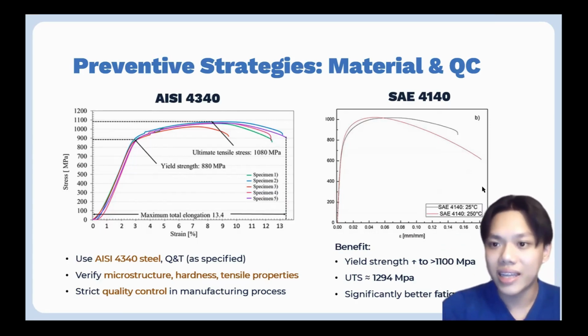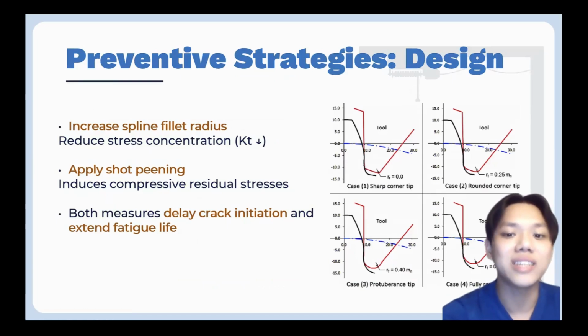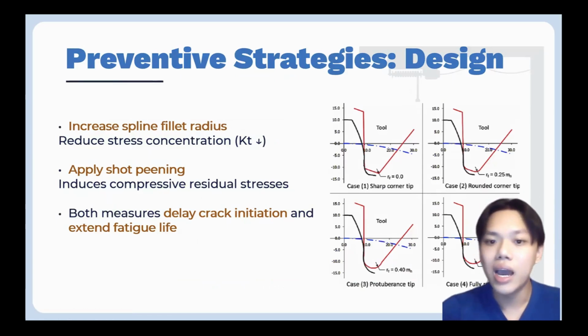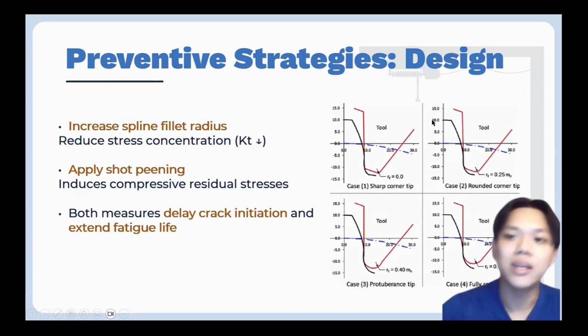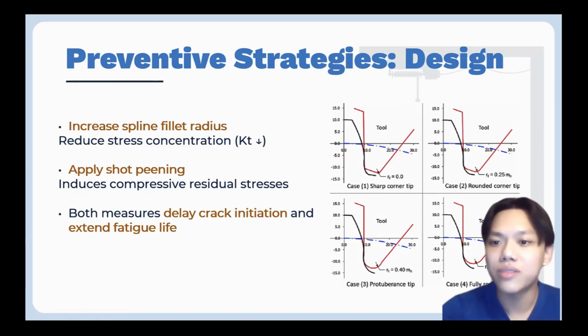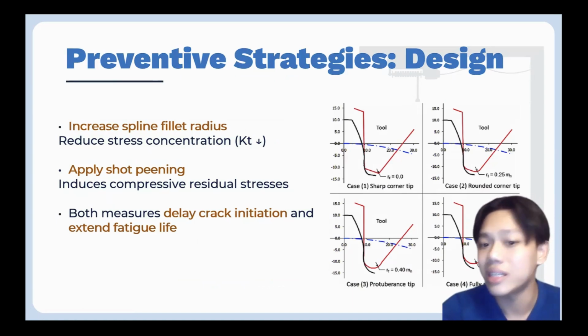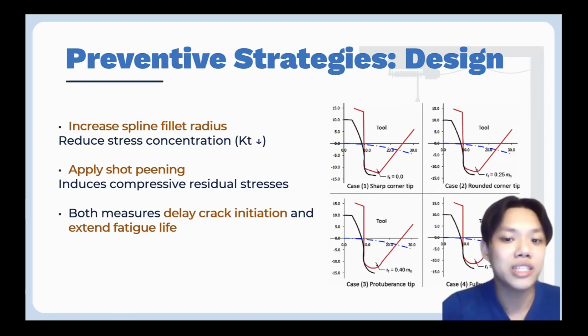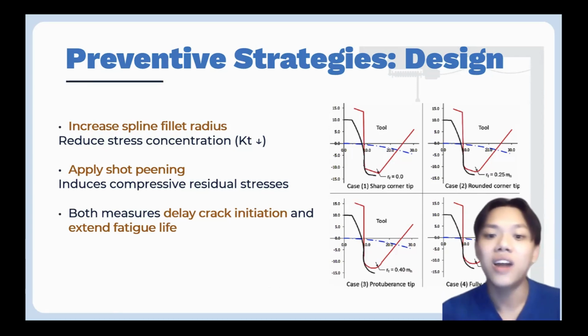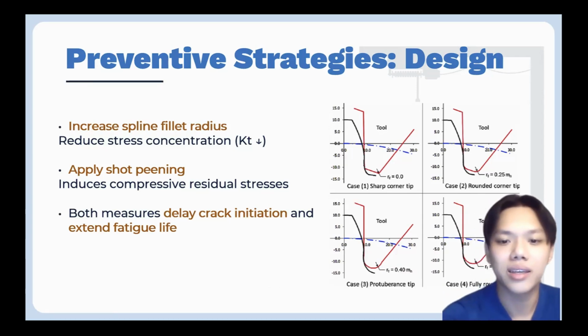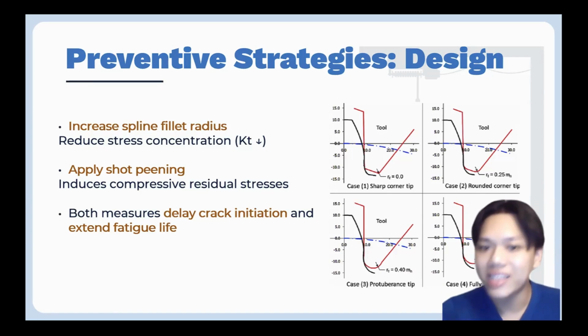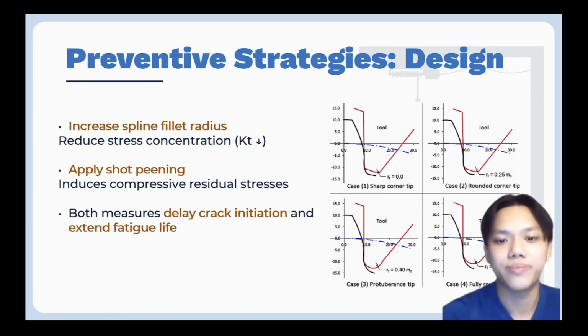Next, beyond the material choice, the design itself can be optimized to improve durability. One key improvement is to increase the fillet radius at the spline root, as in the picture provided here, which compares each radius for the spline. This reduces the stress concentration factor and lowers peak stresses in the region which is critical. Another proven method is shot peening, which introduces compressive residual stresses at the surface. These residual stresses counteract applied tensile stresses, making it harder for fatigue cracks to initiate. Together, these two measures can significantly extend the fatigue life of the half shaft.